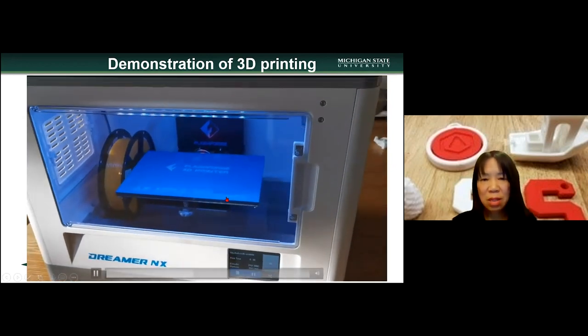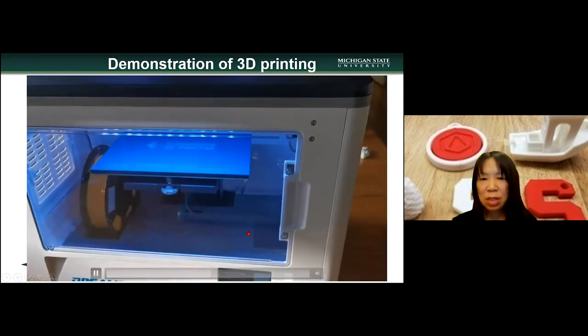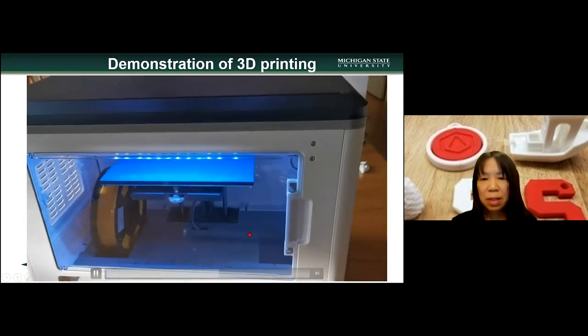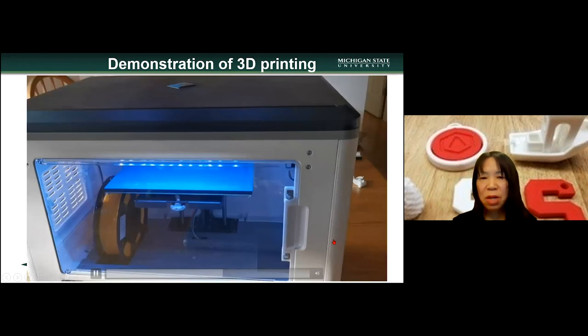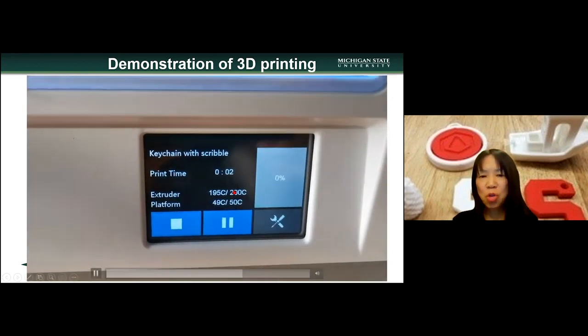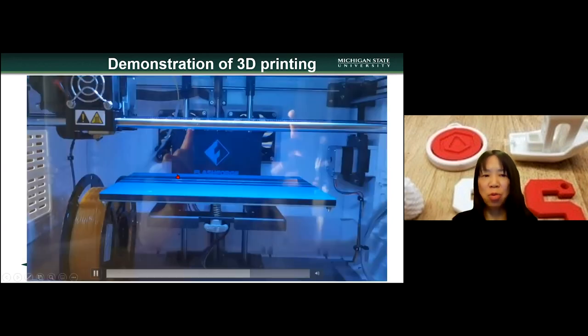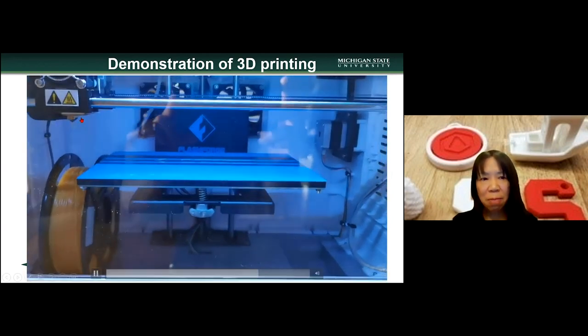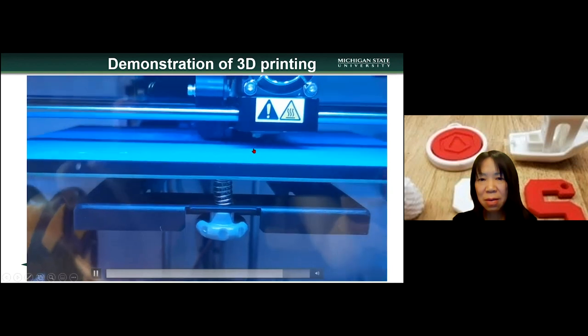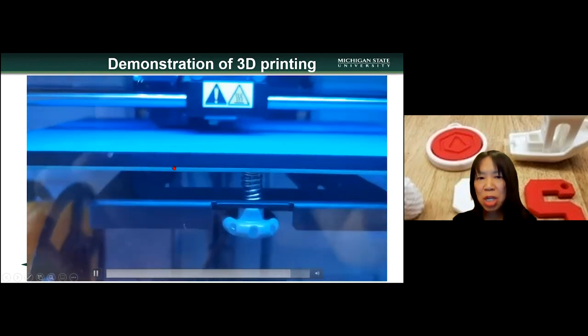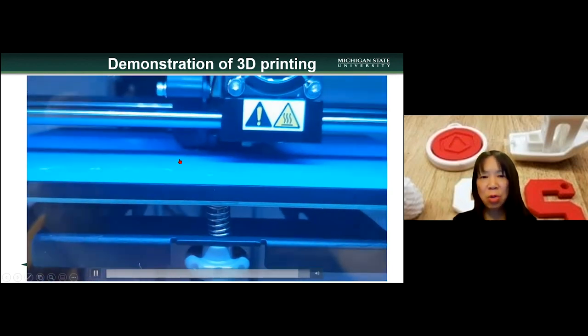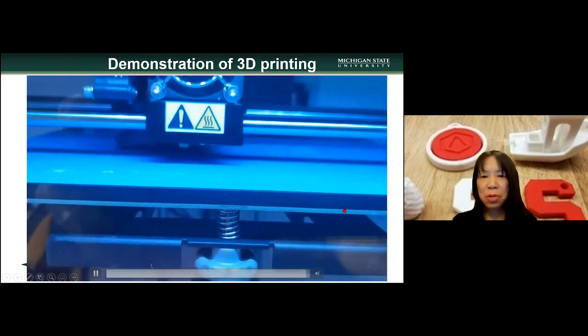keychain. See the platform lift up and then start heating up the nozzle and the platform. Like I said, it doesn't matter what type of printer, it's very similar. So see, the platform is heating to 50 degrees, the extruder to 200 degrees. Now it's ready to print. That's the nozzle, already very hot. You see the material already extruding out, right? Usually the first step is a pre-extrusion, just to get rid of the beginning of the material. Now it's starting to print the keychain.